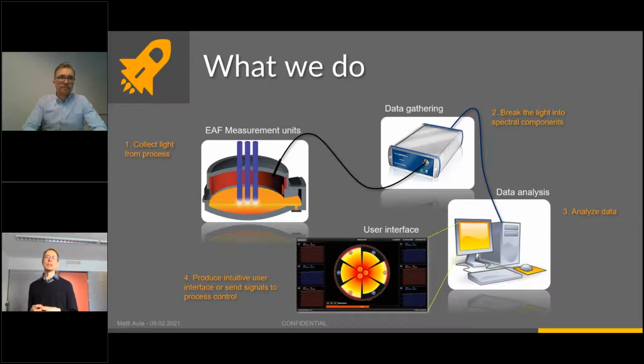So what we do is that we place some measurement heads on the furnace roof. Usually we use three measurement heads, depending on what we want to see in the furnace. We gather the light which is emitted from the furnace. We transmit this light to remotely placed spectrometers. So we have no active equipment on the furnace roof. We can be sure there's nothing in these hazardous conditions. And when we have obtained this spectrum, we analyze it with our homebrew software, and then we present this information either to the operators themselves, in the user interface, or we can also use this information directly to control the EAF process dynamically, straight away through the field bus, for example.